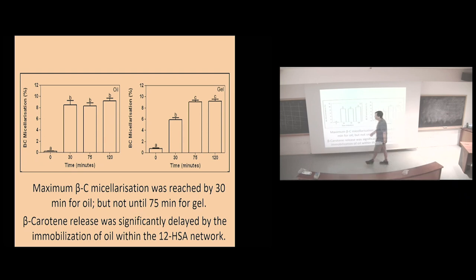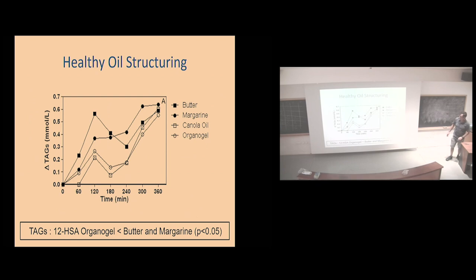And so you can see how, in this case, which would be just the oil itself without the oleogelator, immediately after 30 minutes incubation time, you have just released as much as it's going to release. Now you put it in the oleogel, and in vitro at least, there's a controlled release. There's a slowing down of the release. The oleogel somehow is keeping that beta-carotene in there and preventing the enzyme, after its degradation, from releasing it. So the oleogelation has a role in slowing down that process.